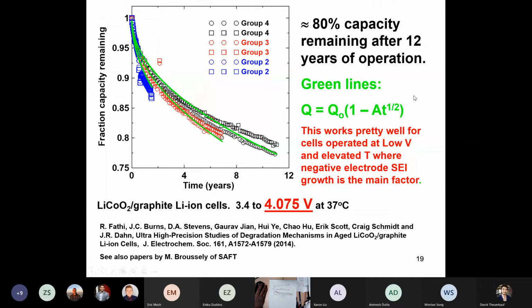And how it is exactly, what exactly its growth rate is, you would need to have some very high level understanding of the film, which doesn't exist. So this works pretty well. And I like it because it's simple to understand how changes to temperature affect A. Increase temperature, you increase A. So I think this is a pretty good way to describe capacity loss when the only thing going on is loss due to the SEI growth.